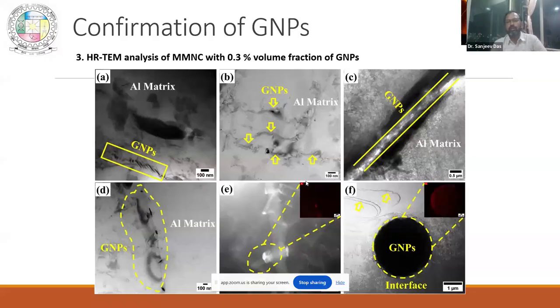So that means the GNPs are uniformly distributed. If it is not uniformly distributed, and we take 2 samples, it is not possible to get GNPs in those samples. So by that we can assume, or we can confirm also, that we have uniformly distributed these particles. And these nanoparticles can only be incorporated by this rotor stator device. If somebody is selling you a normal stirrer, it is very difficult or impossible to incorporate nanoparticles in any liquid metal.